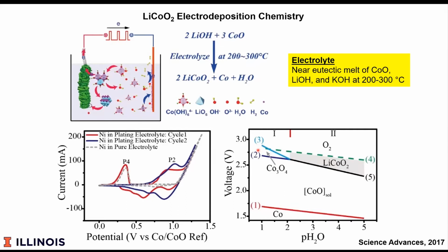So let's back up and look a little bit at the chemistry here. So this is not your normal electroplating that might be done out of aqueous solutions, that's common for most metals. This is an anodic process. We're actually oxidizing cobalt oxide. And as the cobalt is oxidized, then it reacts and forms lithium cobalt oxide. And we do this between 200 and 300 degrees C in a molten salt that's a eutectic melt of cobalt oxide, lithium hydroxide, and potassium hydroxide.